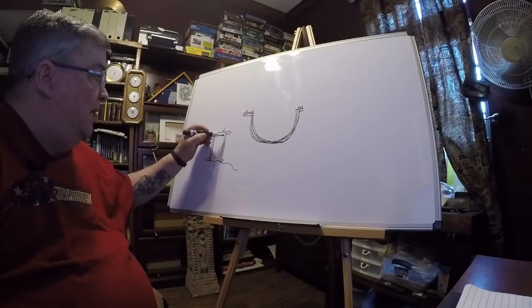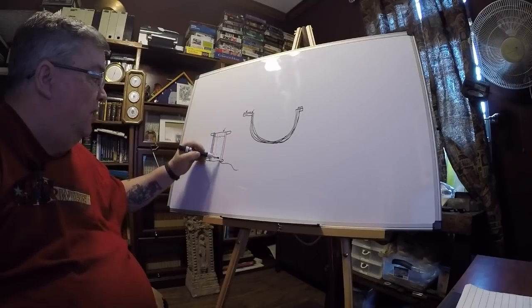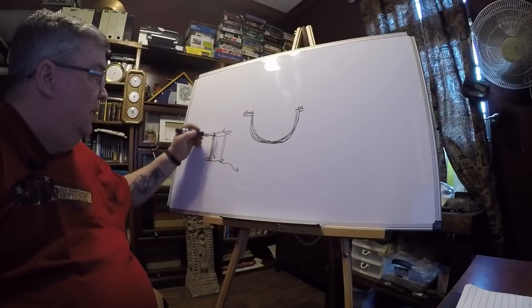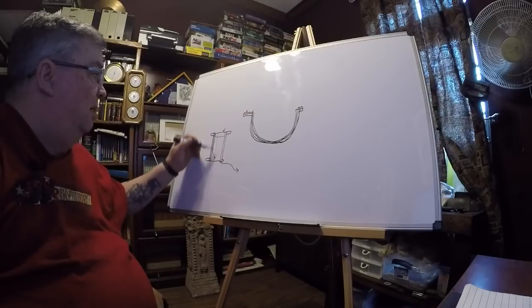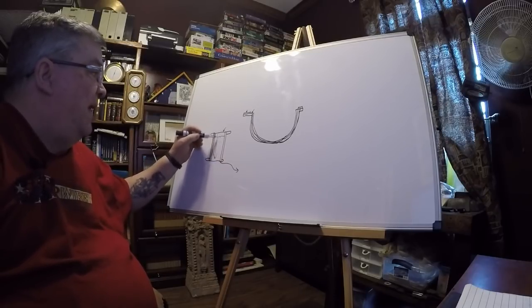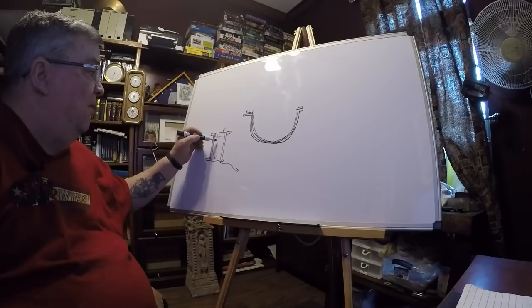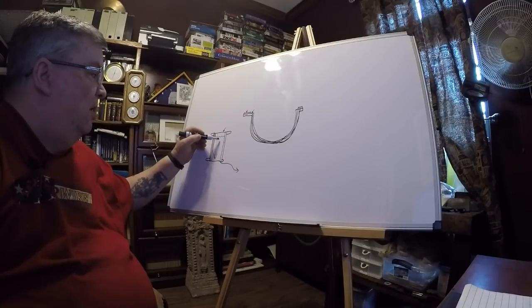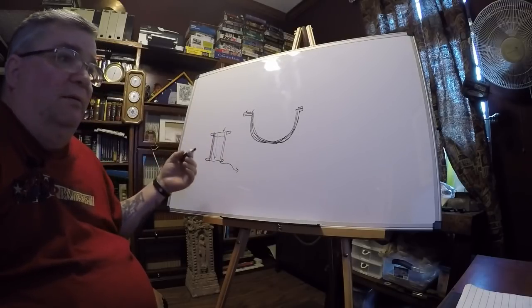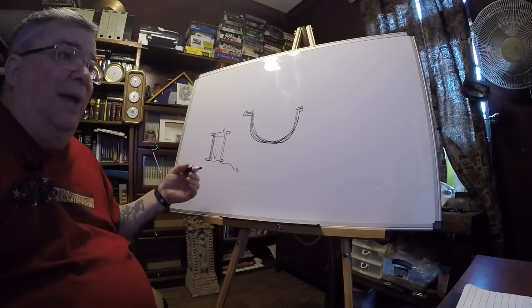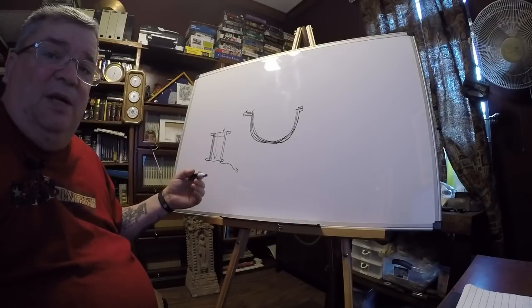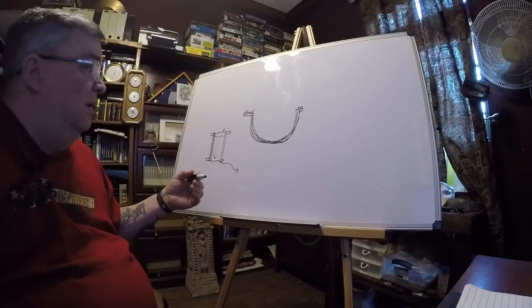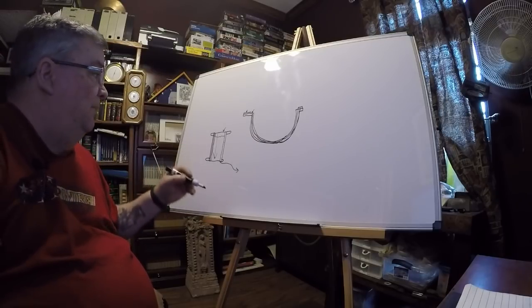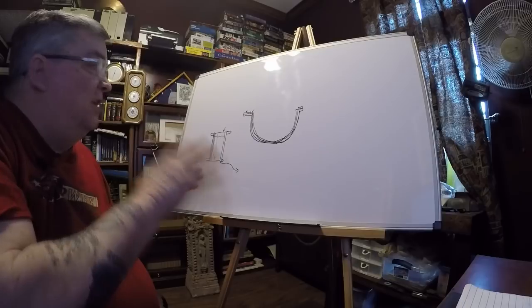After you pour it, you might come up to this point right here and all of a sudden, boom, this bursts, and then it flows downward, it leaks out, and you've got a thin layer of tin adhered to the steel Babbitt shell, and a really thin layer of Babbitt that's going to be oxidizing before you can ever try and pour that again, okay? So you've got to seal all the seals.